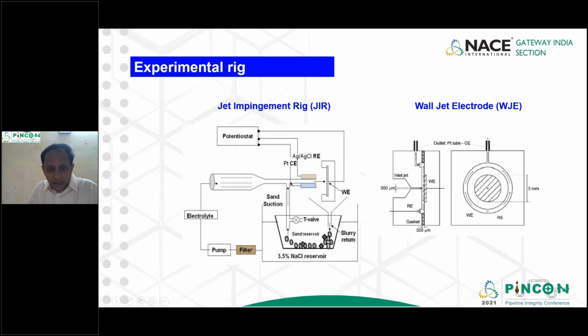I have created facilities here, using a different nozzle. I'm creating a vacuum. By creating a vacuum, the ejector assembly, which is here, is able to suck this sand and maintain a particular concentration of sand, which will go and hit my surface. So in the first experiment, I did the flow corrosion experiment, 3.1 to 6 meters per second. When I did that, I isolated the sand, so I was not taking any sand. Then in the second experiment, when I did erosion, the liquid will come through, sand will go there, and they mix and form a slurry.